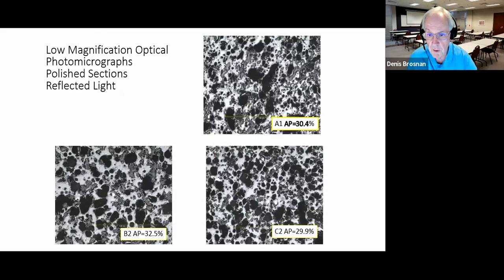Here's cordierite that we made, and they're polished sections on a microscope. This is at very low magnification and reflected light. The black holes, which are mostly spherical here, are pores. So the cordierite we made is pretty porous, and interestingly enough, the pores are reasonably spherical, which means that we had a fairly fluid liquid phase present at the firing temperature for these ceramics. So all the groups produce this kind of microstructure.